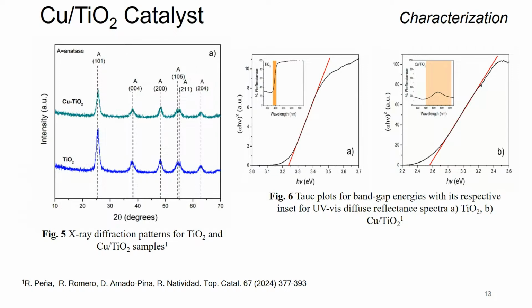By X-ray diffraction, we proved that we had obtained the photocatalytic active phase of the titanium dioxide that most of you in photocatalysis must know, that is anatase, right? And then we also obtained the band gap energies. Here is for the titanium dioxide that we prepared in the laboratory by the sol-gel method. So we obtained a pretty close value to the commercial catalyst. And this one was near to 3.2 electron volts.